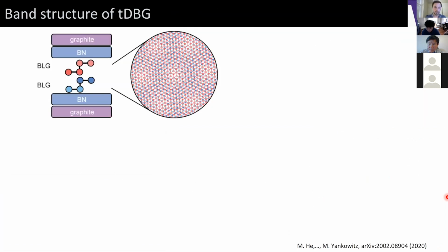Okay, so some of the work that we've been doing, my group in collaboration with Xiaodong Xu's group at the University of Washington over the past 6 months or so, is to look at transport in these twisted heterostructures of bilayer graphene and bilayer graphene, encapsulated in boron nitride with top and bottom graphite gates. These graphite gates allow us to change the charge carrier density as basically the sum of the 2 gate voltages, and the electric field as the difference of the 2 gate voltages.